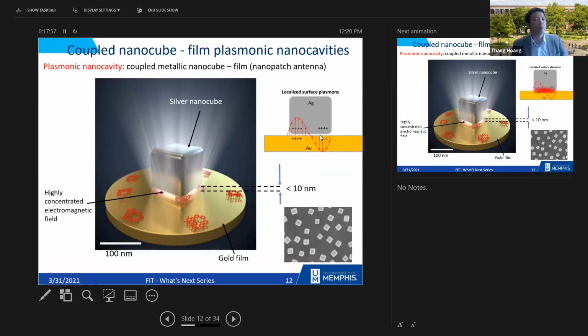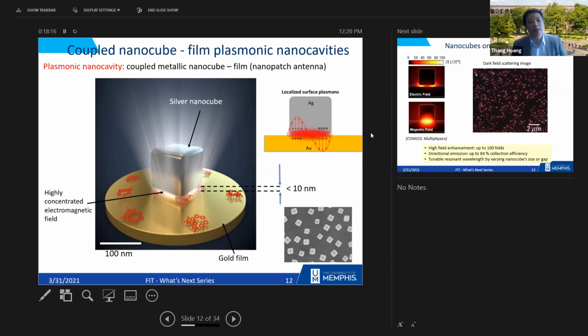And then it forms a plasmon mode, a surface plasmon, a localized surface plasmon in between the nanocube and the gold film underneath. So in the actual sample, it looks like this, a nanocube on top of the gold film. This is an SEM image of the sample. And the really interesting thing is that in the volume between the nanocube and gold film, the electromagnetic field is very enhanced, it's very strong. Okay, so we want to make use of that.